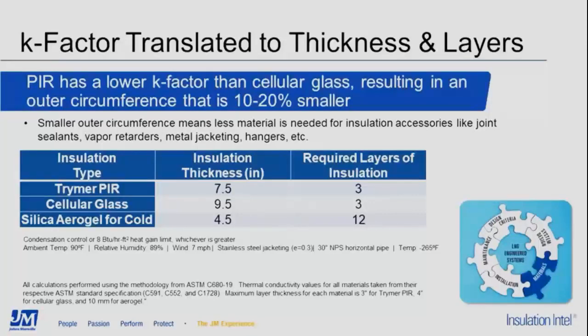So even though the silica aerogel in this particular example of 4.5 inches of thickness is less total thickness than PIR, it's 12 total layers because each layer of aerogel is 10 millimeters or a little less than half an inch of thickness. This is a limit of the aerogel products. They only come in a maximum of 10 millimeters thickness. I don't understand the full manufacturing process, but for whatever reason, the aerogel only comes in a thickness of 10 millimeters, so you need a lot more layers to install the aerogel, and each layer has to be individually installed. It's not like they're all glued together into one installed device made up of multiple layers. You install each layer individually. So where you would install 3 layers of PIR, you'd have to individually install 12 layers of aerogel, even though the total thickness is 4.5 inches compared to Trymer's 7.5 in this case. I hope that answers the question.